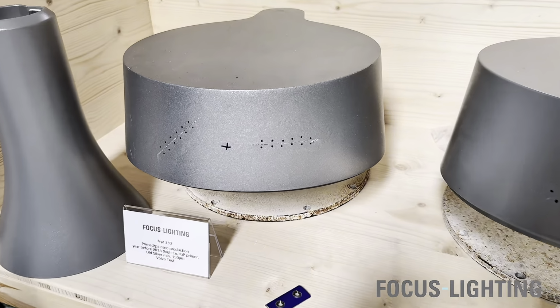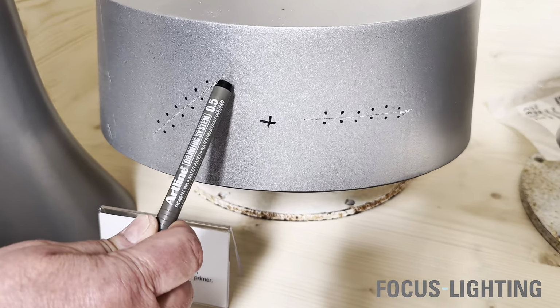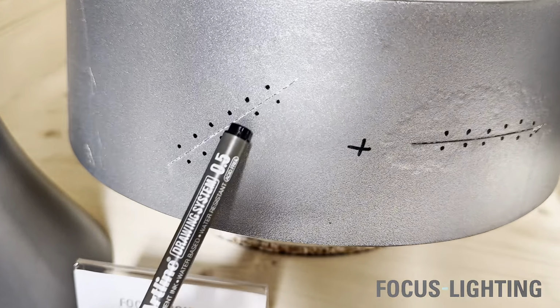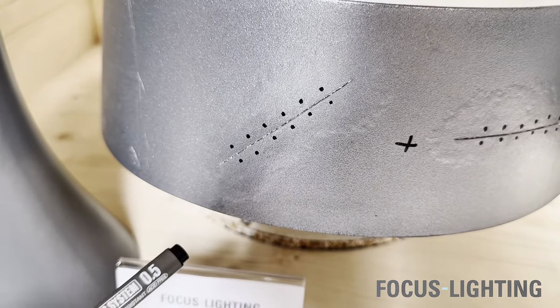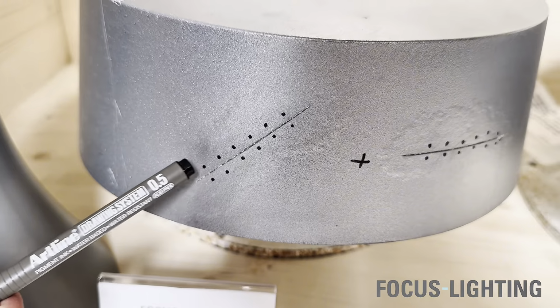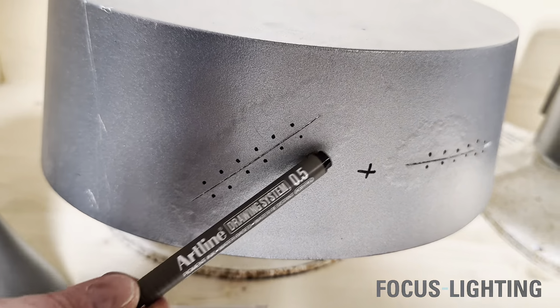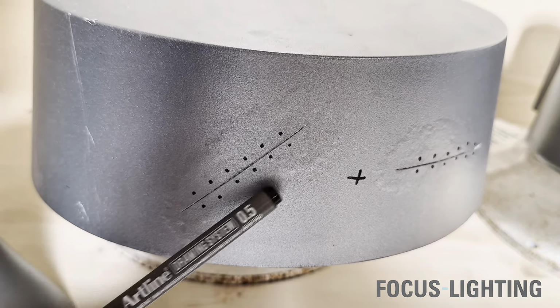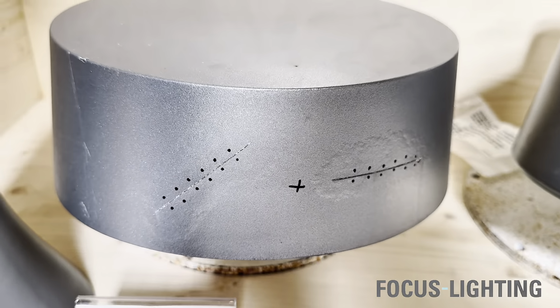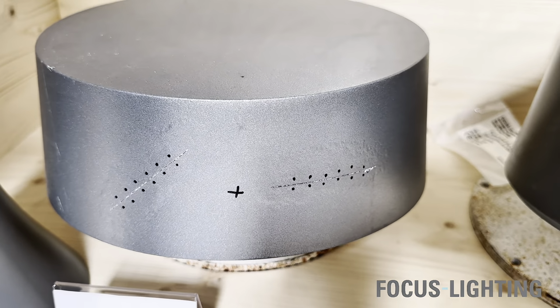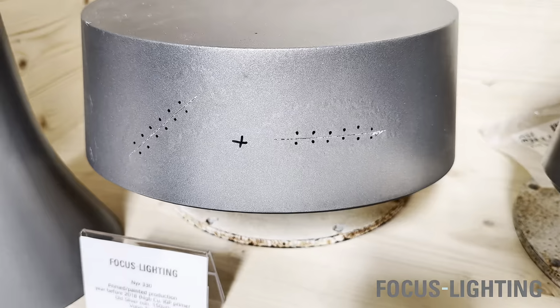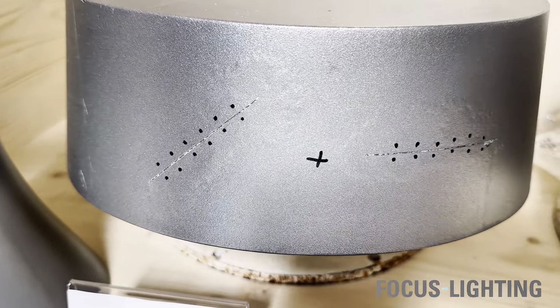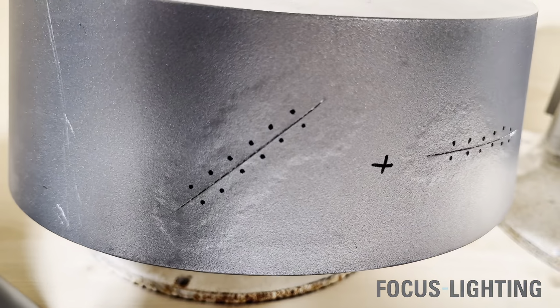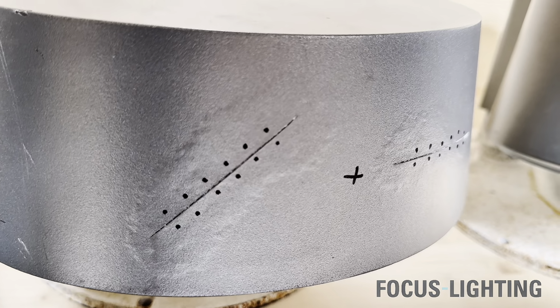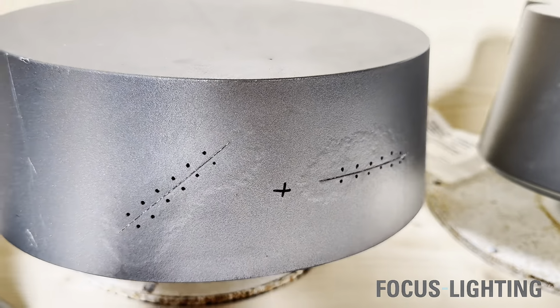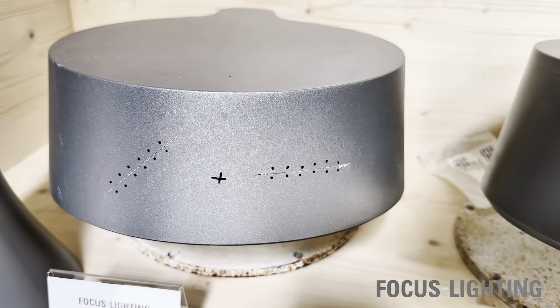If we go close to this luminaire, you would see the scratch that is made on day 1 in the test procedure. And then you can see you have blistering around the scratch, which is actually the beginning of a corrosion process where the primer and the top coat would be peeling off after a certain number of years. This is after 10 years, and it's not to a satisfactory quality.